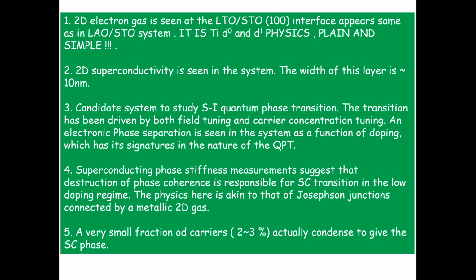So what we have is a two-dimensional electron gas seen at the interface of LTO-STO, and it appears to be the same as the gas we see at the interface of LAO-STO, as far as all the measurements that we have done. So what we conclude is that it is simply the physics of titanium d0 and d1, and all the action is happening at the interface in strontium titanate.